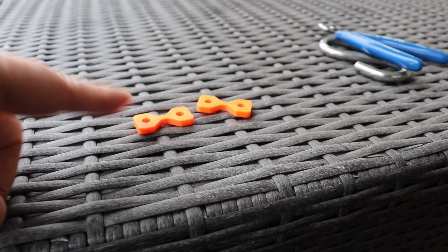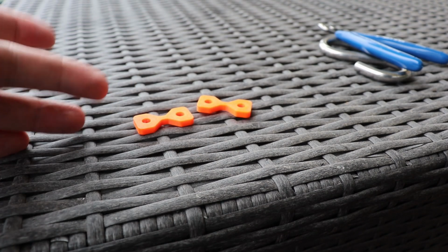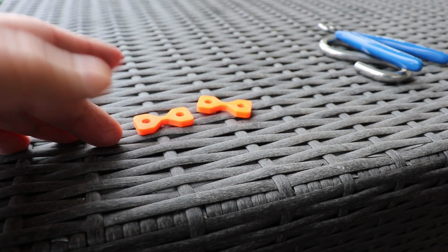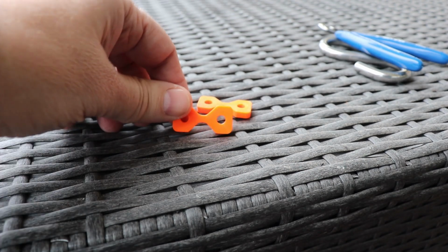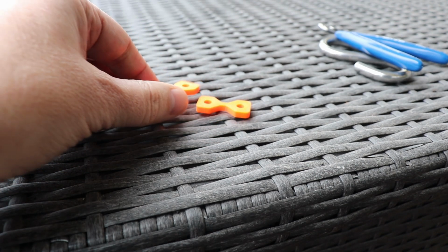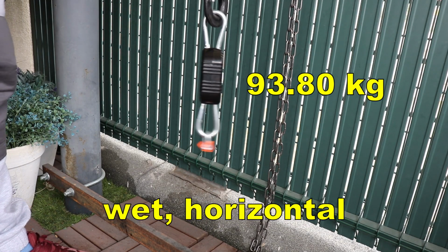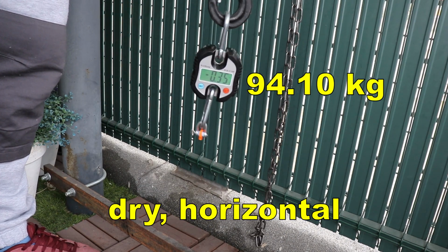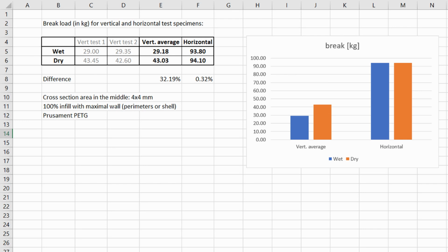And this test is less important. This test specimen is printed in horizontal position, and I just want to check if there is any difference, but theoretically there shouldn't be any difference in the tensile strength between these two printed objects. And these are the results. As I predicted, no significant difference on specimens printed in horizontal position. And those printed in vertical position, well, the difference was quite big, 32%. So yes, definitely the first one was really wet filament, and it has a very big effect on layer adhesion.